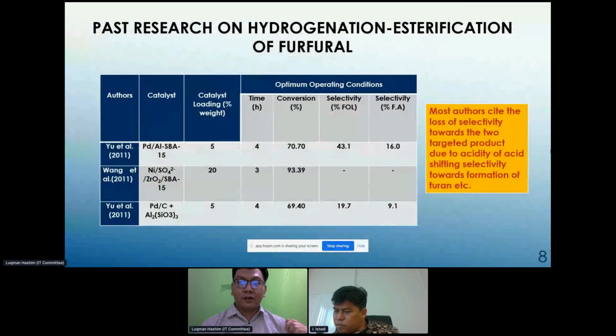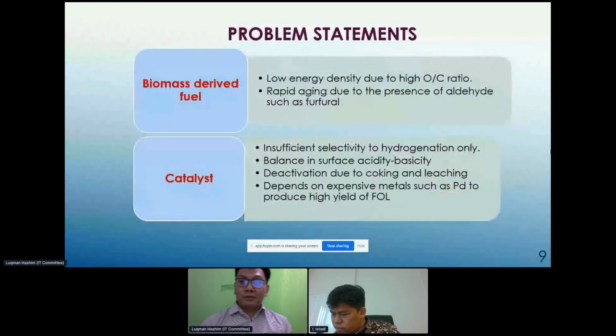Now, specifically for hydrogenation and esterification of furfural in tandem, that means one after another in one pot, the main problem I would say here, as you can see, is the low yield and selectivity towards furfuryl acetate. Why is that? It's because of the low selectivity towards furfuryl alcohol itself, which will be the starting material of furfuryl acetate in this tandem reaction. And again, they apply palladium, which is relatively more expensive compared to the other transition metals that we are studying today.